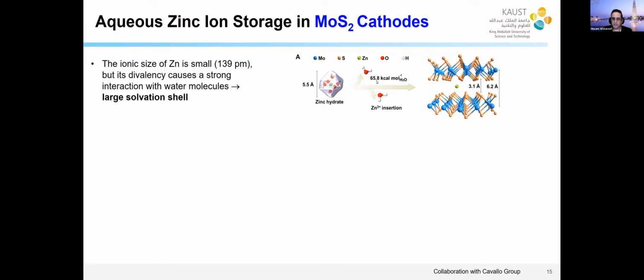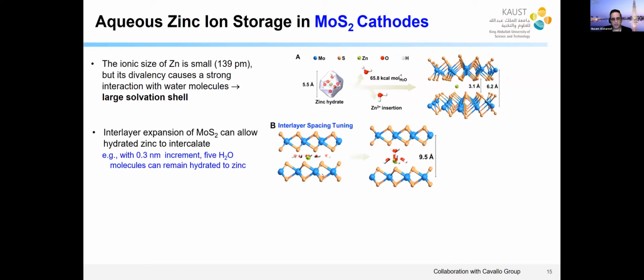First, you have to expend some energy to try to remove the water molecules. And the question is, what can we do to expand the spacing? It may be easier to leave the water around the zinc because actually this reduces electrostatic repulsion. So is there a way to expand the interlayer spacing in a reliable way for the zinc, the molysulfide, so we can intercalate the hydrated zinc? That was the question. So we did some calculation and then we found out just a 3 angstrom increase in the interlayer spacing of the molysulfide can allow you to intercalate 5 water molecules surrounding the zinc. So this will greatly facilitate the intercalation process.